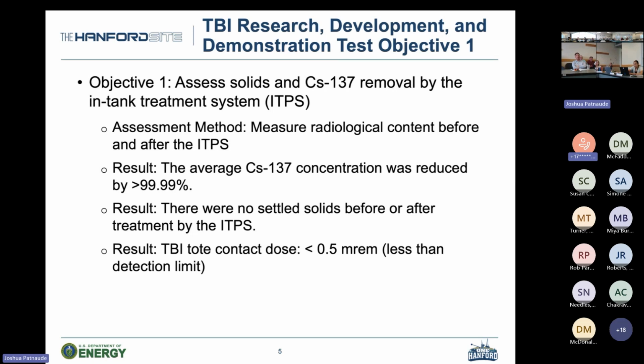But again, the first objective was the removal of cesium, which we demonstrated. 99.99% of the cesium from what was in SY101 was removed by the ion exchange columns, based on the sample results in the storage totes. And again, no settled solids were found inside the transport totes following the test bed initiative treatment. Radiological surface dose was less than 0.5 millirem. And we couldn't measure less than that because the background radiation was about 0.5 millirem.